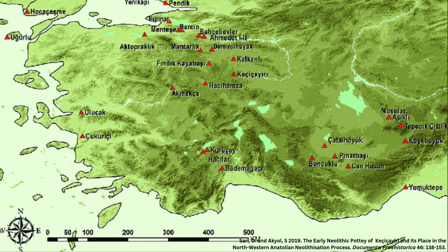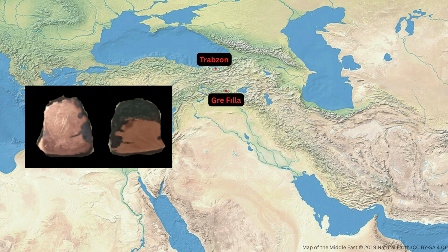I won't be surprised if we find more evidence for early experimentation with pyrometallurgy at other sites in the region because lead isotope analysis revealed that the source of the copper for the bar-shaped object was not the mines nearby, but most likely Trabzon, by the Black Sea, suggesting that the raw materials were acquired through trade or exchange. The dawn of the Neolithic may be an overlooked and yet important phase in early pyrometallurgical developments.